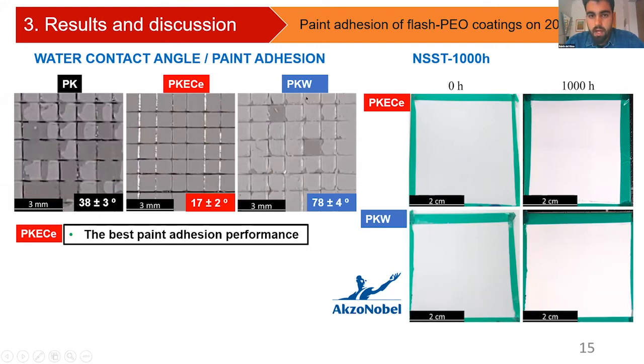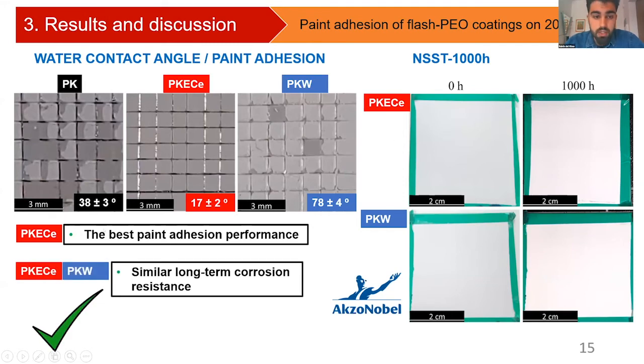for 1,000 hours. For both inhibitor-containing PEO coatings, we obtain similar long-term corrosion behavior in both cases. And also we didn't detect any blisters or pitting, formation of pits during the test.